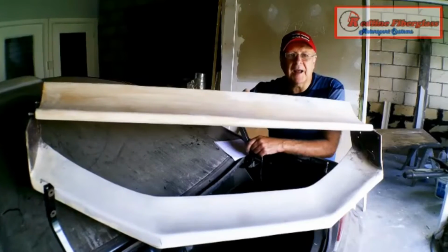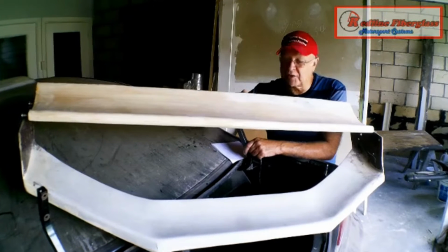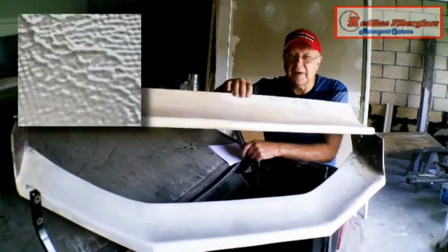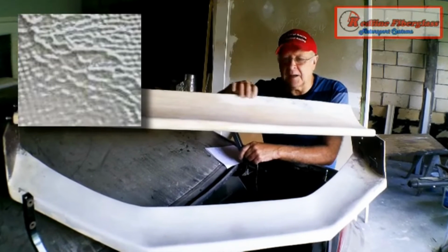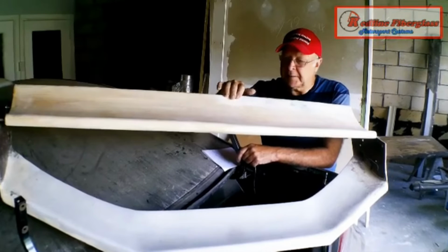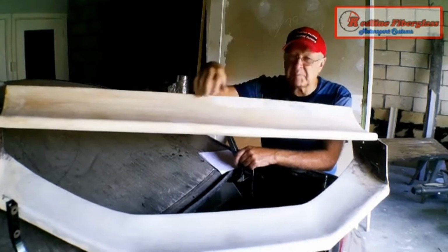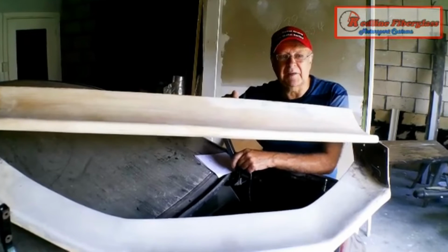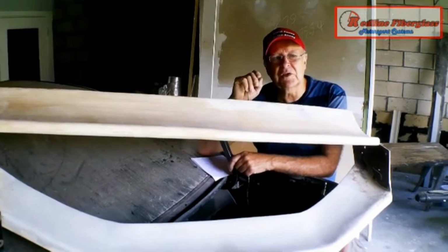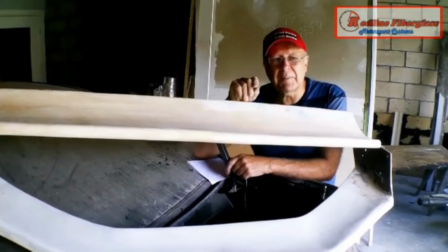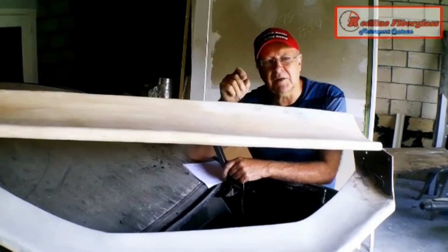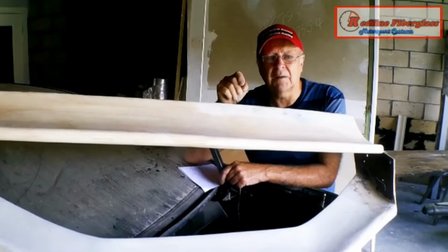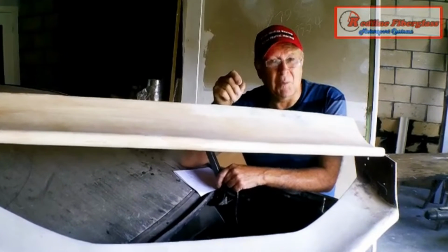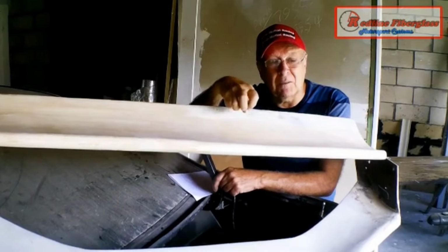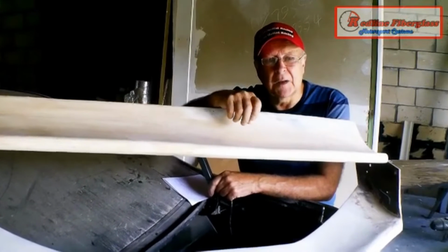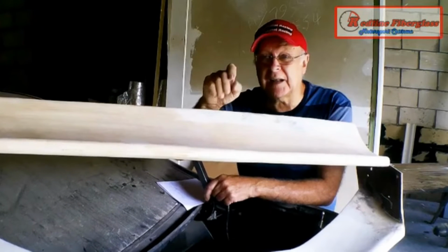Alligatoring is the term used to describe when you get an undesired wrinkly finish in your fiberglass, sort of like an orange peel surface. You don't get it on the whole job, you just get it in places. The cause of alligatoring is generally that your gel coat was too thin. And what happens is when you apply the poly resin with the cloth over the top of your gel coat, the resin, as you know, gets quite warm as it goes off, and it will buckle that gel coat under that heat. So your gel coat needs to be thick to withstand that.